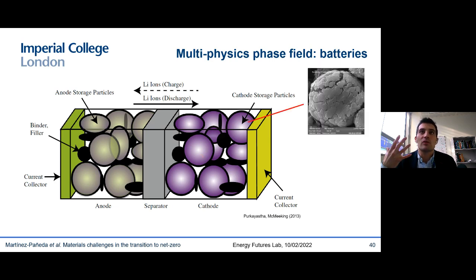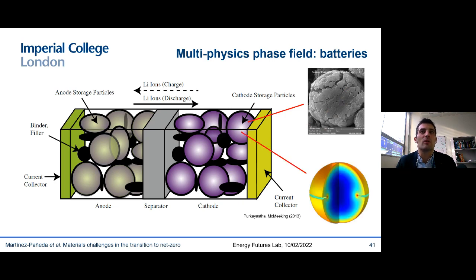And this continuous cyclic shrinking and swelling of these storage particles leads to the appearance of these cracks, which basically degrade battery performance. So our goal here is to develop models that can predict the nucleation and growth of these cracks and the resulting degradation of battery performance. And we want to predict this as a function of the material and charging conditions. We want to again map safe regimes of operation and inspect the viability of new material solutions.